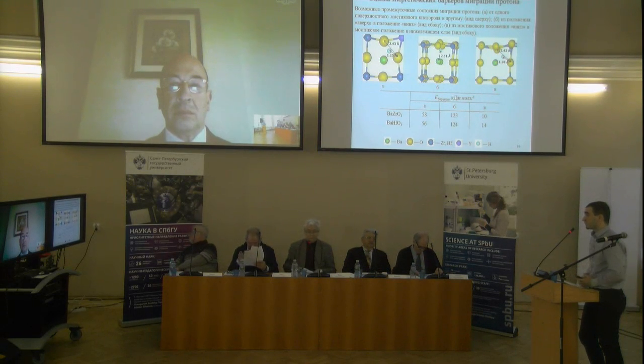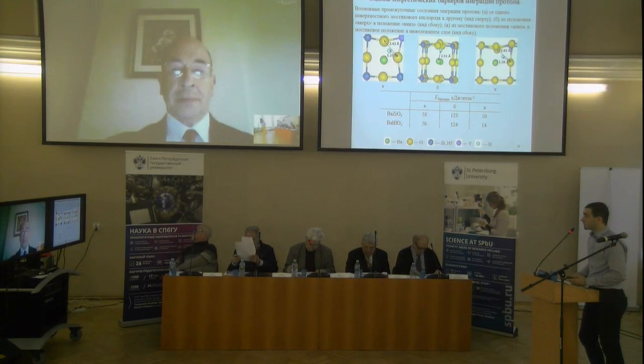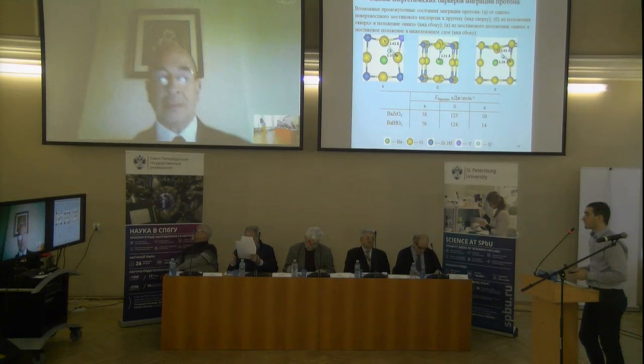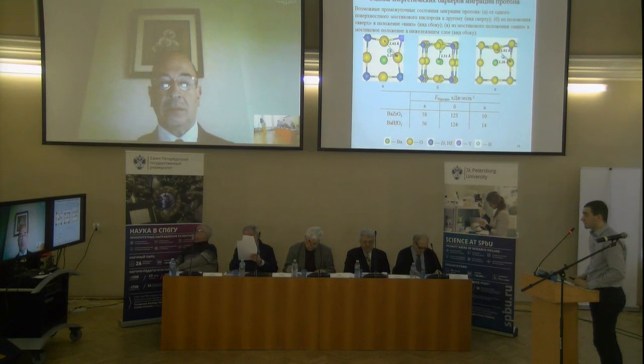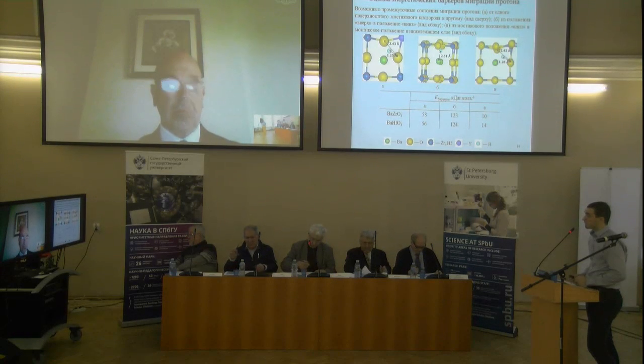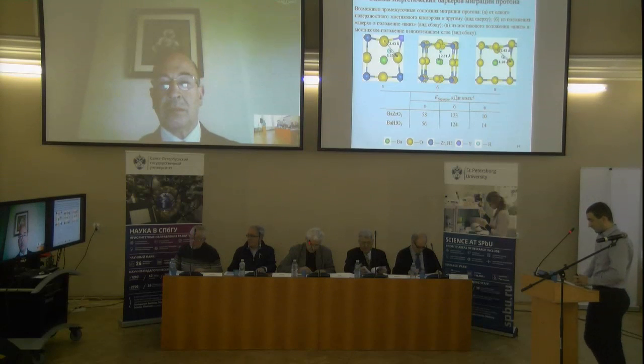The value of the water absorption energy depends on the orientation of the resulting bridged hydroxyls. In the first case, the bridged hydroxyls are bonded to one common Zr or Hf atom, while in the second case to the common atom Y. It should be noted that the absorption energy in the first case is higher than in the second. In the third calculated case, the bridged hydroxyls are parallel to each other and do not have common Zr, Hf or Y atoms. This structure is the most advantageous.